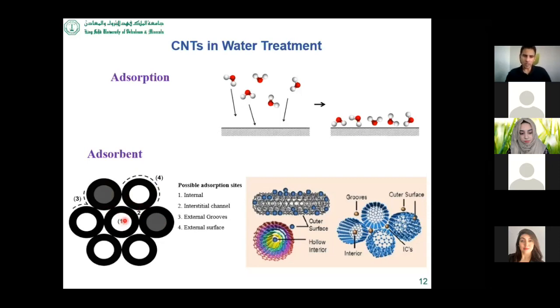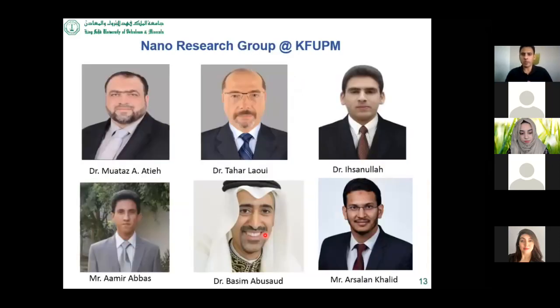And these four are various sites where different molecules can be adsorbed on the surface of these carbon nanotubes. So it can be adsorbed inside the carbon nanotube itself if it is open, between the channels, and on the external grooves and external surfaces. Of course, I'm talking here about non-functionalized or pure carbon nanotubes. If you functionalize or modify the surface of the carbon nanotubes, then the number of these adsorption sites can be enhanced. Our group at KFUPM has worked extensively in this area, and we have published more than 100 papers specifically focusing on the application of carbon nanotubes in water treatment as adsorbent, functionalized carbon nanotubes, production of carbon nanotubes, and carbon nanotube-based composites for various applications, mainly environmental applications.